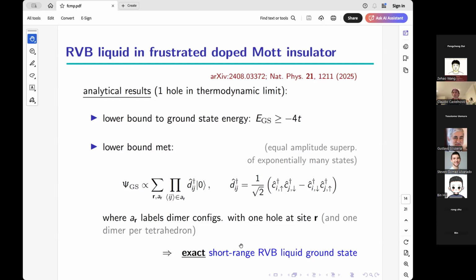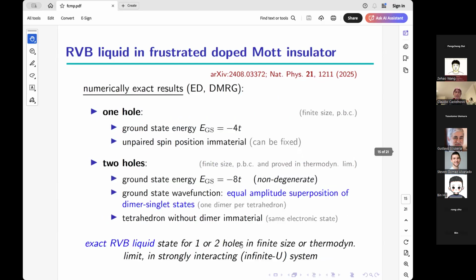It is the exact short-range RVB liquid ground state that people would have dreamt of. Interestingly, the beauty of the result doesn't stop there. It's not only exact in the thermodynamic limit, it's exact for any finite-sized system with periodic boundary condition. There are no finite-sized corrections to this system. The ground state remains minus 4t, hence Didier's result back in the days when he did ED, of course, was for finite-sized systems, and it was exactly minus 4t, not minus 3.99 or anything else.